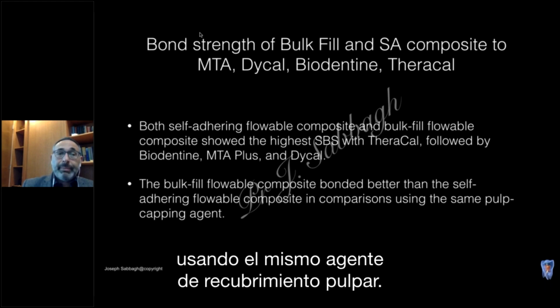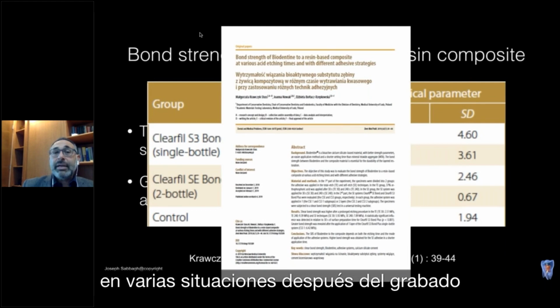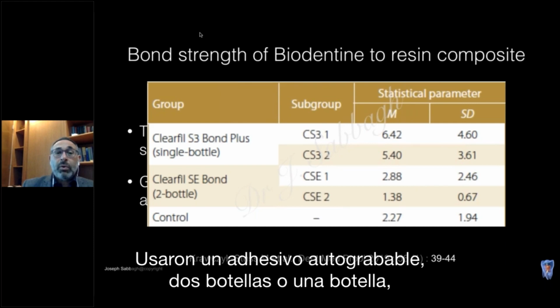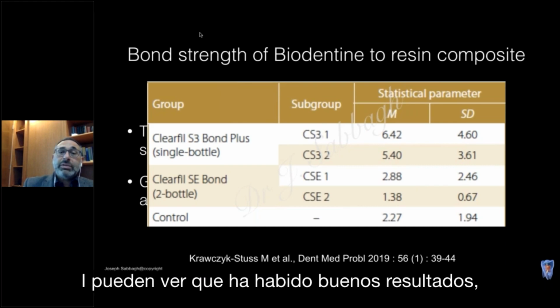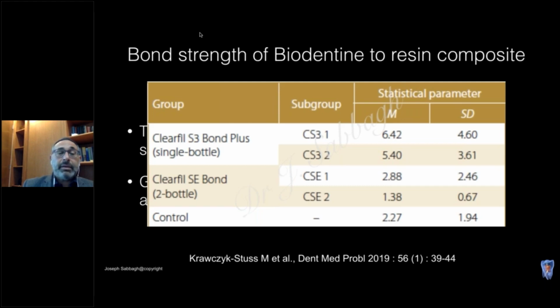Finally, this study also pointed out the bond strength of Biodentine to a resin-based composite at various etching times and with different adhesive strategies. So they played on changing the etching time that could bring better adhesion or not, and they also used two different types of adhesive from the same manufacturer, from Kuraray. They used a self-etch adhesive, two bottles or one bottle, and always with Biodentine. And you see that we had good results, 6.42 megapascal with the Clearfil S3. So this was one step. And the conclusions were the following.